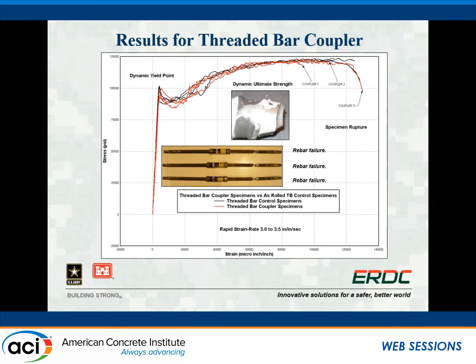And then finally, the best performing couplers that we found at dynamic loading conditions were threaded bar couplers. You can see these stress strain curves almost overlay each other, at least to an experimentalist. We get really similar tensile strengths, similar ductilities, and as you can see in these triplicate samples, all of them fail outside of the coupler. They fail like they should, and we get good performance.